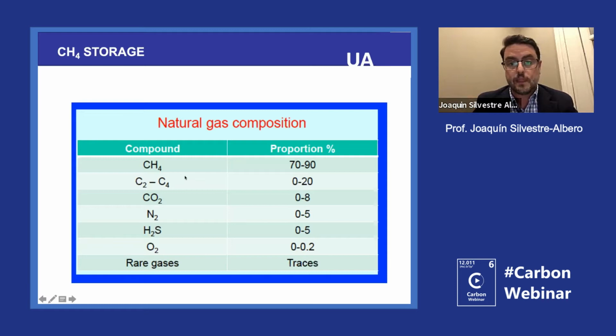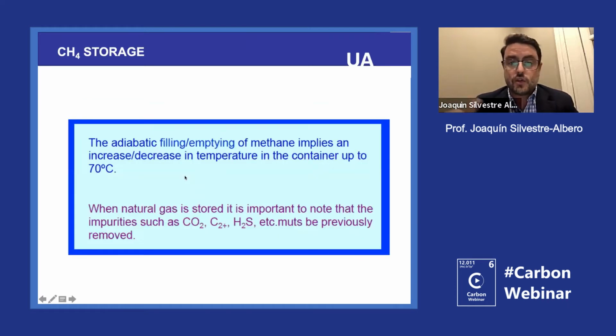In a second cycle or third cycle, because some of these molecules can be retained in the porosity of the material. And another thing that I will not show you today is the thermal conductivity issues, no? When we are talking about a cylinder and we are trying to incorporate a carbon material in the inner side of the cylinder, we have to be aware that adsorption is exothermic.